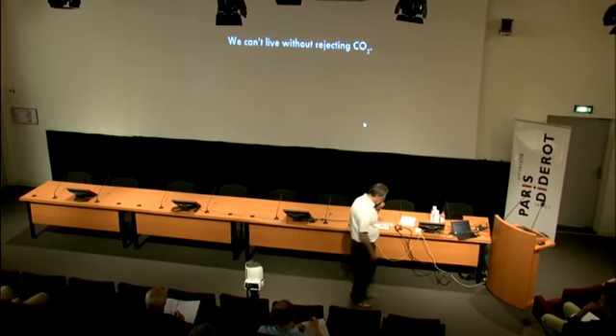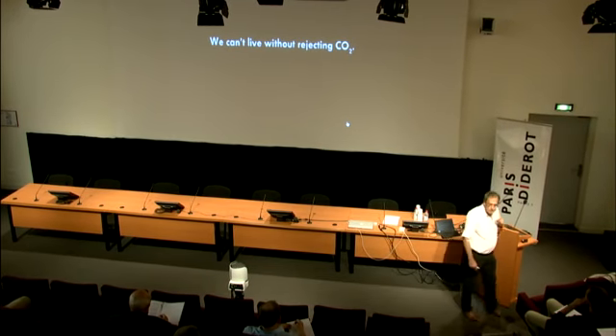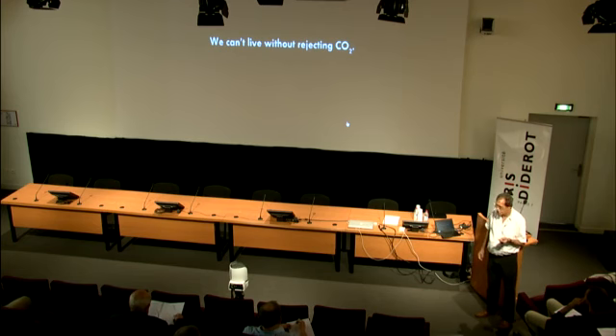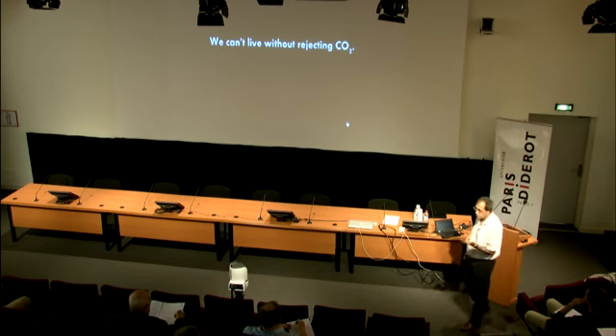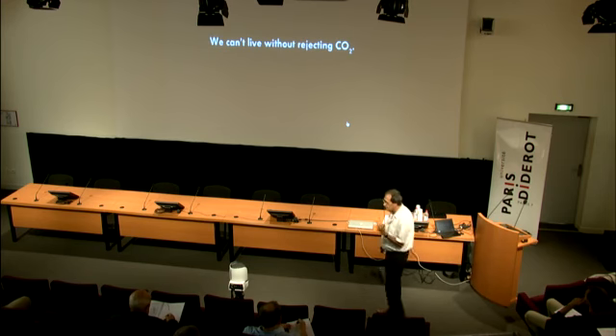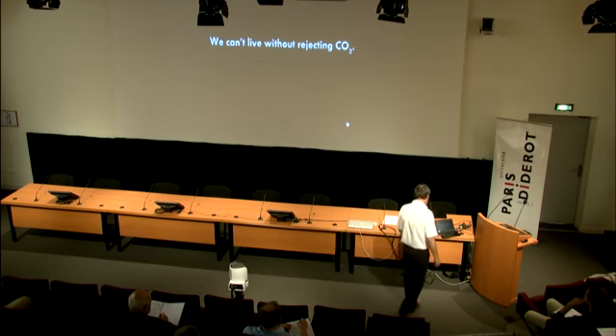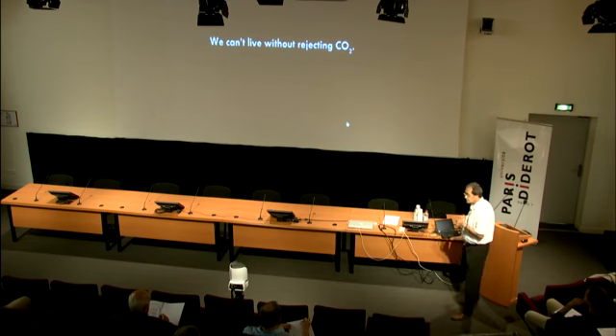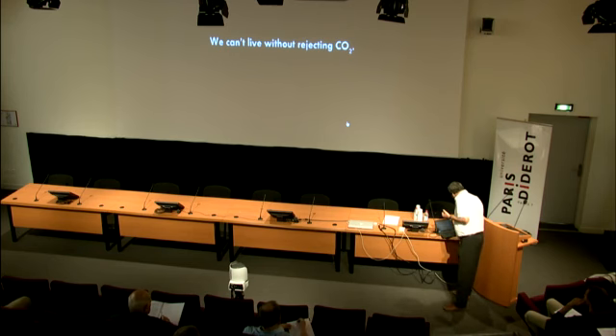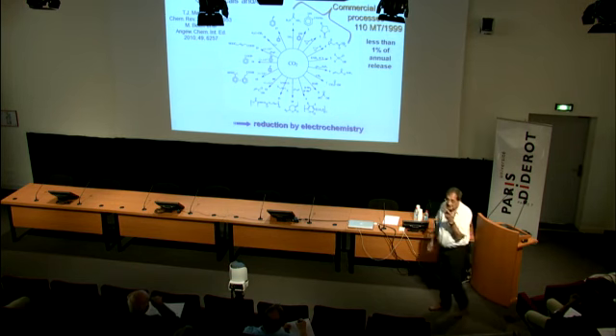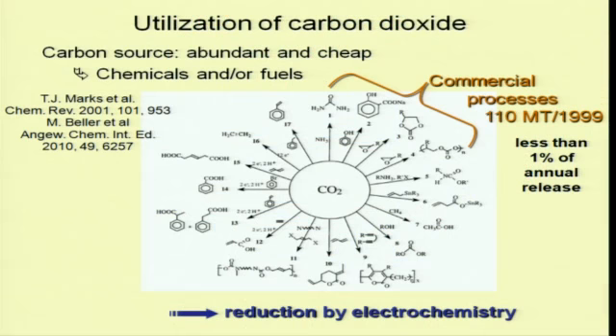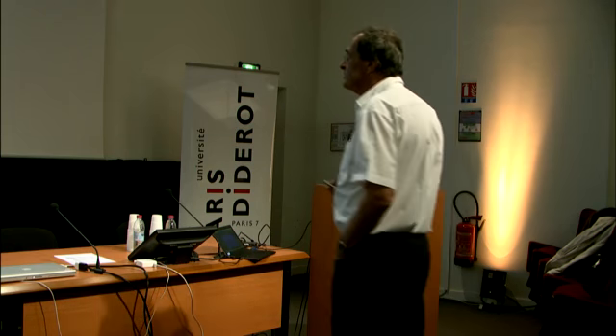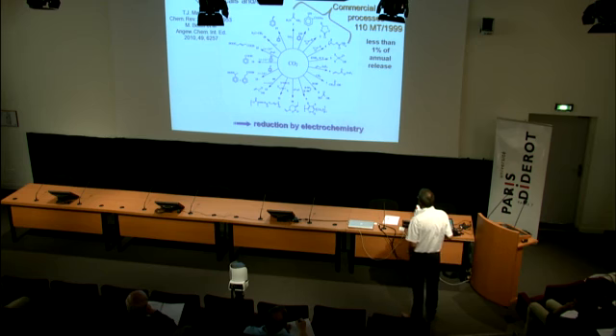The problem is that CO2 has to be activated, because CO2 is the most oxidized form of carbon. And it's necessary to reduce or at least activate it by a catalytic process. And if you look at the utilization of CO2 in industrial processes, you can see here the situation at the end of the last century. There are only 4 commercial processes. And look, the consumption is less than 1% of the annual release. As I said, there are only 4 commercial processes: making urea, salicylic acid, and organic carbonate.